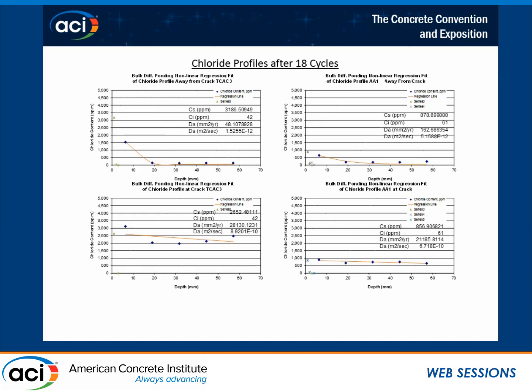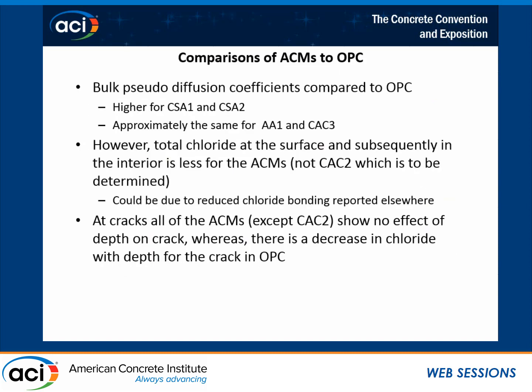Type C fly ash with activator had a pretty low one to start with, about like an OPC, but once again, at the crack, it gets much worse. So the effect of cracking on these alternative cements is much more severe than it is for OPC. So anyway, in comparison among them, we see the pseudo diffusion coefficients are higher for CSA1 and CSA2, approximately the same for the other two alternative cementitious materials.